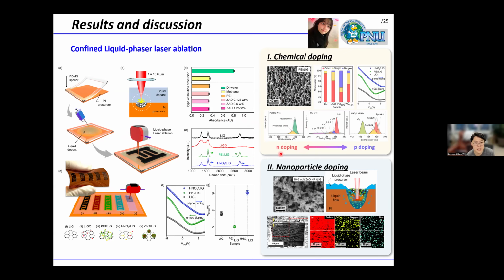In addition, by incorporating the metal precursor into the dopant solution, we can also synthesize porous graphene decorated with metal nanoparticles, as shown here. So one of the advantages of this confined liquid ablation method is that when we expose the laser, the liquid phase of dopant is continuously fed at the reaction site. So we can uniformly dope the LIG system in the depth direction.